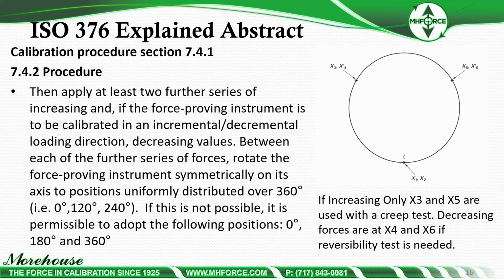Then we're going to apply 2 further series of increasing values, and if the force proving instrument is to be calibrated in incremental, decremental loading directions, decreasing values. Between each of the further series of forces, rotate the force proving instrument symmetrically on its axis to positions uniformly distributed over 360, namely 0, 120, 240. If this is not possible, it is permissible to adopt the following positions, 0, 180, and 360. So basically here, we're going to move the instrument.